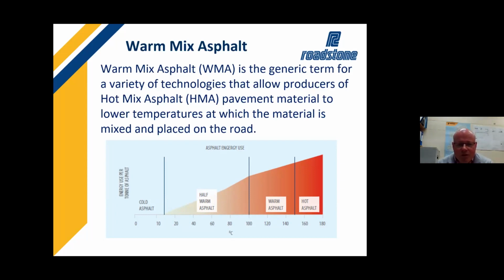Now, typical materials are made from 150 to sort of 180 degrees temperature. Your warm mixes are made anywhere up to 100 to 140 degrees is typical. After that, you're going into your half warm mixes or your cold mixes, which typically are emulsion based. Warm mixes are typically made with standard hot bitumens, but you have those additives that allow different things to happen in the mix.